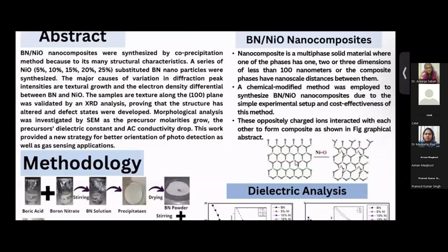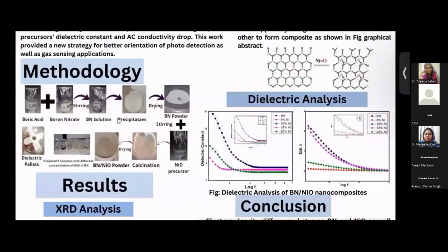Methodology. Boric acid and boron nitrate, which is used as the first precursor, are mixed and put on a stirrer for 2 hours, and the precipitates are obtained. The precipitates are further kept in the oven at 80 degrees centigrade for 2 to 3 days. The boron nitride powder is obtained. The boron nitride powder and nickel oxide precursors are mixed together, and then the boron nitride nickel oxide powder is obtained.